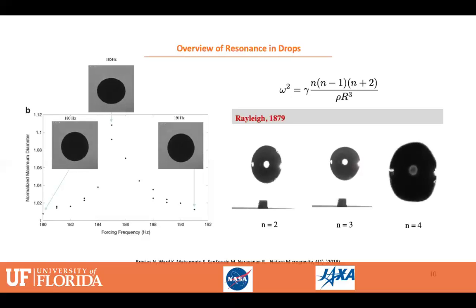The important thing to note is that if you do decide to use liquid metals on a ground levitator and want to measure the surface tension, inevitably you'll have to have the atmosphere as vacuum. Because if you try to levitate a very heavy metal, say in argon or nitrogen, very typically the DC voltage needed to levitate the solid and ultimately to create a liquid from it is so large that very often short-circuiting or arcing will take place. So one way to get away from this is to try to do the levitation in space, where you do not need a very great amount of forcing to levitate the solid and to make it into a sphere.